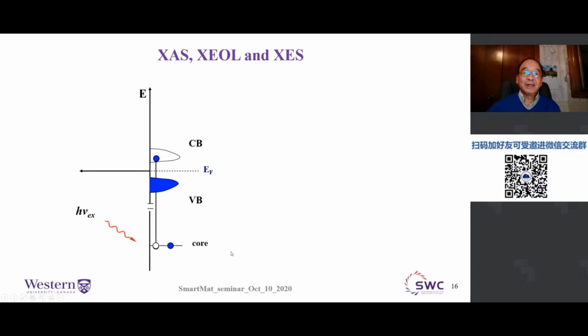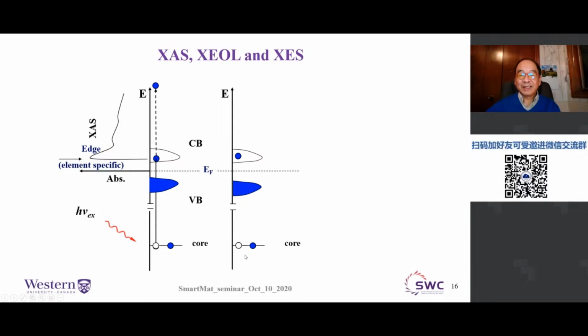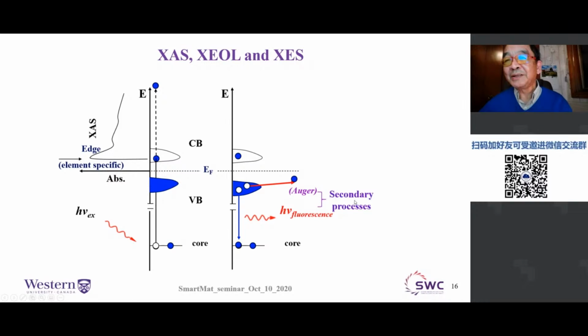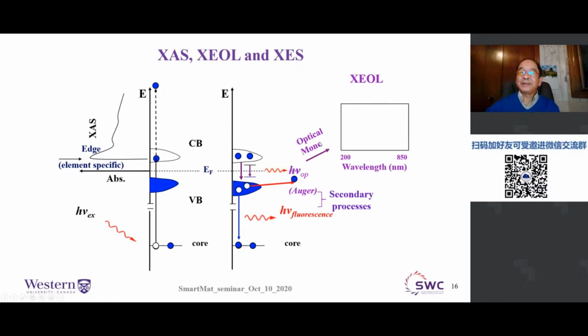So let's say you have a semiconductor, you excite it above the core edge, you get your absorption spectrum, right? And then the system is in an excited state with a core hole, then the electrons can fill it. And the de-excitation process can be Auger and X-ray fluorescence. And these two processes can undergo secondary processes, and the end result of that, of course, is to give you electrons at the bottom of the conduction band, holes at the top of the valence band, and they can combine to give you optical photons. If you use an optical monochromator, then you can track it, and you can see the bandgap emission, and you can see the defect emission, right? With a tunable X-ray, it can be site-specific, because you get the excited atom preferentially.